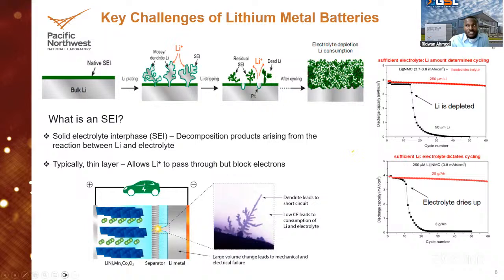Remember, I talked about this dendrite, this tree-like structure. One of the problems it can cause is that it can grow in such a way that it's going to penetrate through the separator and have contact with the other side of the battery, which is the cathode. And that is not good. It can cause fire, because that is what we call a short circuit. So those are the challenges surrounding lithium metal batteries.